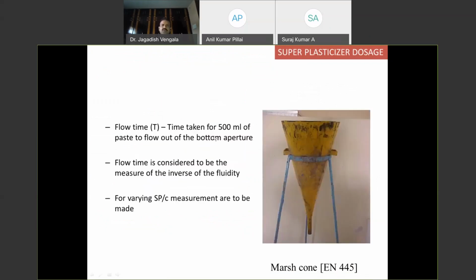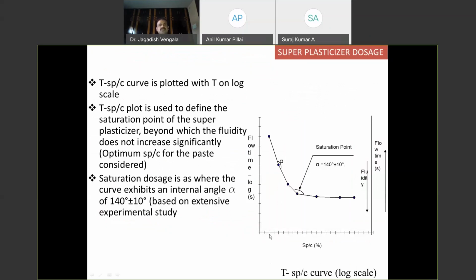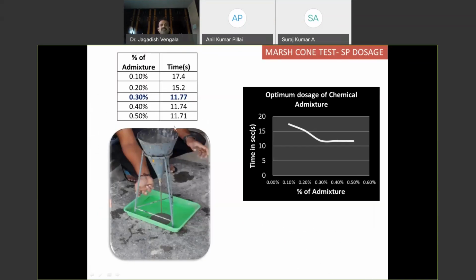What you do is prepare 500 ml of paste, pass it through the Marsh cone, and measure the time taken to flow through the bottom aperture. Then you draw the graph between flow time versus superplasticizer to cement dosage. Typically the curve will be like this, and there is a saturation point. You can see here some of the percentages of admixture dosage. We start with 0.1, where the flow time is 17 seconds, then 15.2, and at 0.3 it is 11.77. After that, there is not much change. So 0.3% is the optimum dosage based on the Marsh cone test. So superplasticizer dosage and compatibility between cement and superplasticizer can be taken from the Marsh cone test.